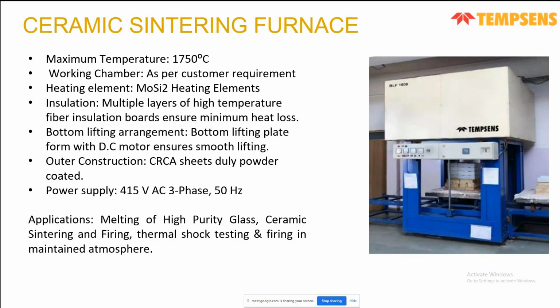This is a large bottom loading furnace. So this one our customer is using for ceramic sintering. So this is up to 1700 degrees centigrade with molybdenum disilicide heating element, and the bottom lifts up, and you can have a charge which is sitting here, and this hot part which is coming out can be moved out. So they all can be done according to your requirement. So they can be used for melting of high purity glass, or for ceramic sintering, or for any other application of yours.